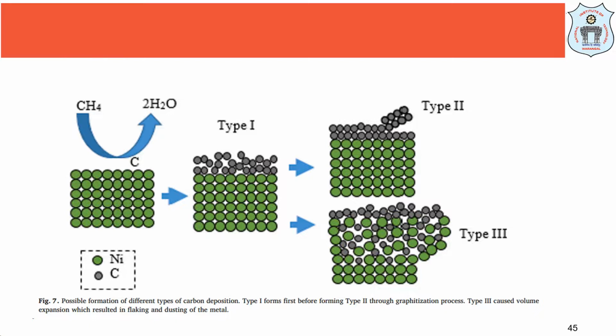So in this figure you can see some of the possible formations of different types of carbon deposition on a nickel anode material. Initially, carbon will start depositing at the surface of the nickel. But still it will be porous enough to allow the gases to pass through, that is methane or any reactant, and the surface reaction takes place. But later on it forms a type 2 formation, because initially the type 1 deposition takes place, after which the carbon starts forming a monolayer, double layer, and so on, which will retard the migration of reactants into the reaction sites.